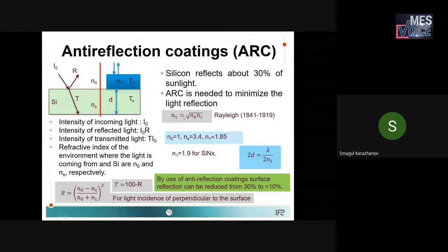This relationship was found long time back by Sir Rayleigh. This is the refractive index of the anti-reflection coating material, this is the refractive index of air that will be above the coating, and this is the refractive index of the main material underneath the anti-reflection coating. For silicon, the refractive index is 3.4. The refractive index of air, above the anti-reflective coating, is 1. It means the anti-reflection coating material should have about 1.85.